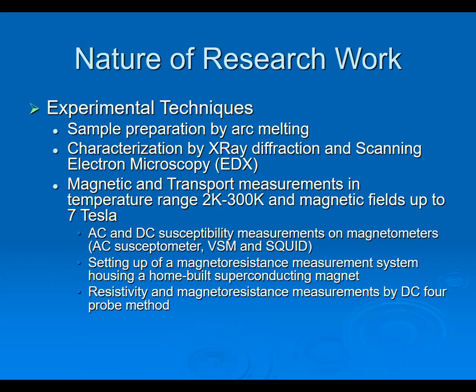So these were some of the experimental techniques that most material scientists would have to do. So my sample preparation, when I say arc melting, is because I was essentially working with metallic specimens. And there is a furnace, you have to wear all these dark glasses, like welder's glasses and so on. A very interesting experience in itself.